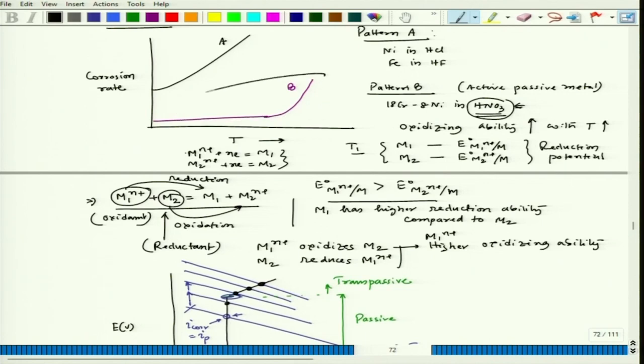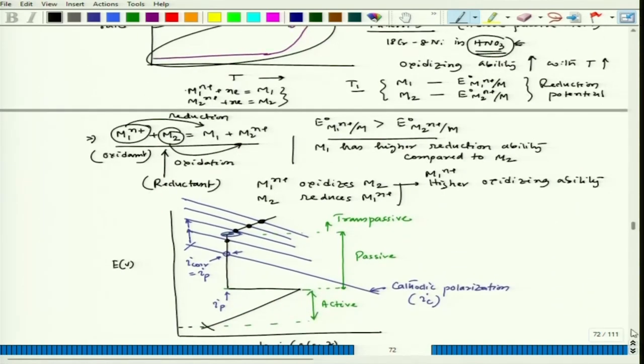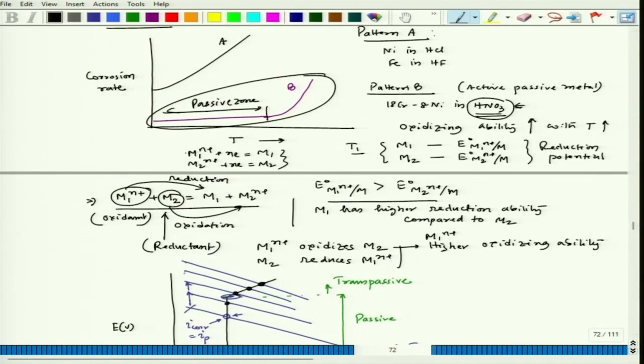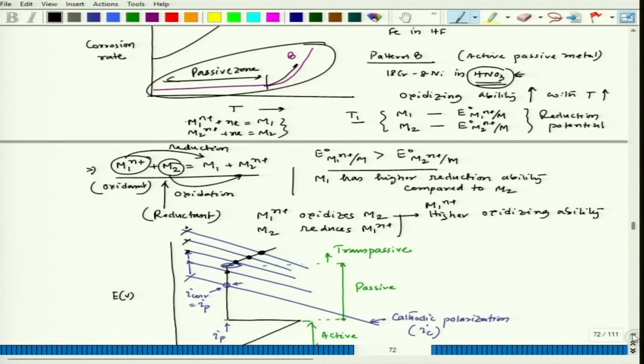Initially, up till this point, it maintains the passive zone, and as the oxidizing ability increases, the reduction potential goes up, and the corresponding cathodic polarization line cuts the active-passive anodic part initially in the passive zone, and then goes into the transpassive zone. So, that is why the corrosion rate again increases like this. This is typical of 18Cr-8Ni stainless steel in HNO3. So, this is the effect of increasing oxidizing ability of the corrosive with increase in temperature.